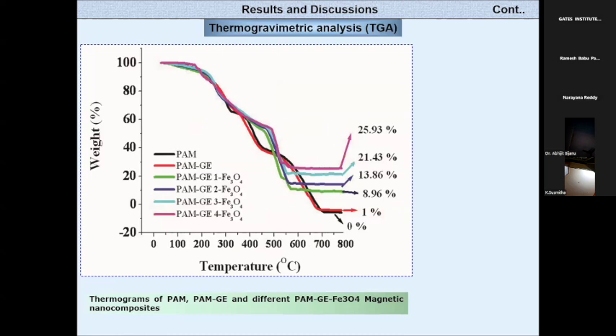We also look at how much nanoparticle content is there in your hydrogel network. If you increase the gelatin content, it attracts more ions, so you get more nanoparticles in your polymer network. Of course, if you reach a certain level, it will reach the maximum equilibrium state, and beyond that you don't get any more nanoparticles.